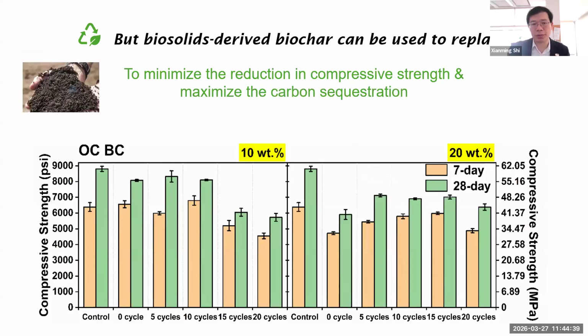However, for the biosolids derived biochar, we were able to get to a reasonable balance. When I say balance, I mean achieving reasonable compressive strength of the mortar samples, and at the same time, getting some carbon credit, basically sequestering as much CO2 equivalent as possible. So we were achieving a reasonable balance. Again, we did try to optimize the number of cycles we have to subject the biochar products to in order to get the right amount or right size of carbonate. That's a lot of trial and error.